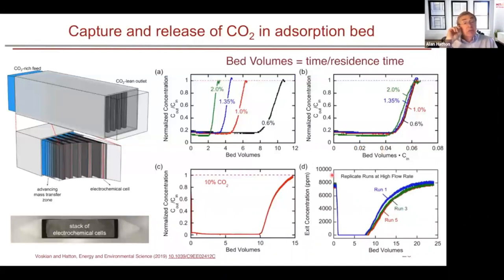We've also done this in packed bed type operations. This shows the normalized concentration in a packed bed. We have a packed bed like this. We have a CO2-rich feed, and we measure the outlet concentration. This is a normalized concentration, outlet over inlet, as a function of the number of bed volumes. Bed volumes is equal to the actual time of the experiment relative to the residence time within the bed. And what we'll notice is that initially the CO2 has been absorbed, so what's leaving the column here is a very low CO2 concentration until such time as the bed is totally saturated with that particular concentration, and therefore the concentration of the effluent rises to be up to the feed concentration.